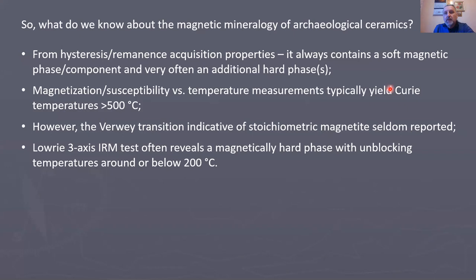They always contain a magnetically soft phase, and very often one or two magnetically hard phases. By magnetically hard phases, I mean those phases that have coercivities in excess of 100 millitesla.